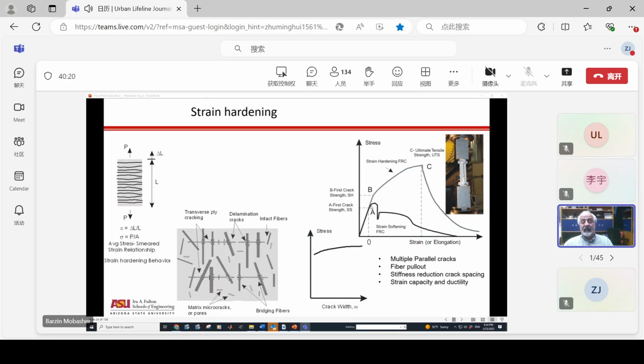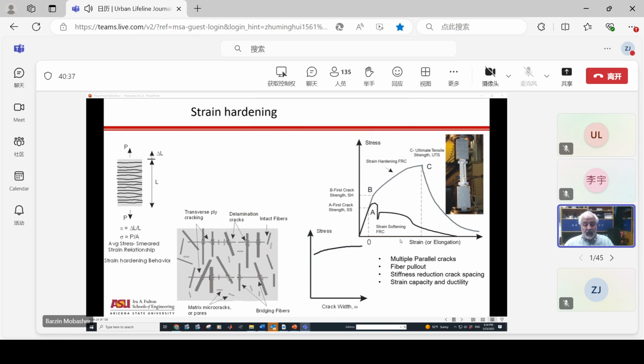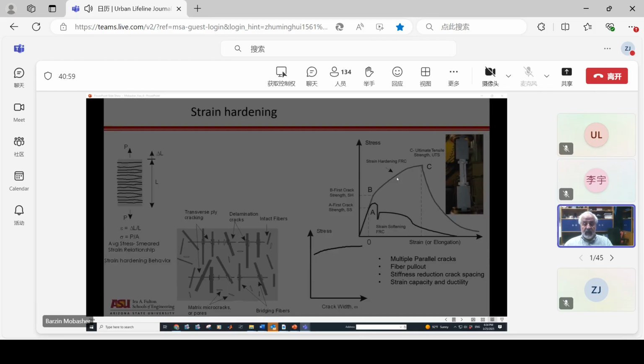Now I'm increasing the strength. Now I'm having a material whose tensile strength is almost twice as much, and my stress crack width relationship could be treated as a plastic type of curve. So this is actually really good, but it's costly. Let's say the cost of UHPC is defined by this model, whereas strain softening is for conventional material. But the criteria for strain hardening is that we must get some kind of a parallel crack system. We should get fiber pullout that's controlled, and actually we can calculate the stiffness, and the stiffness reduction here can be used for our design.